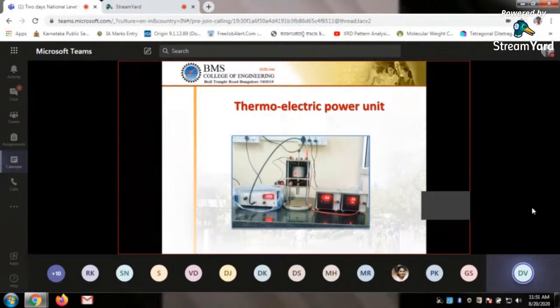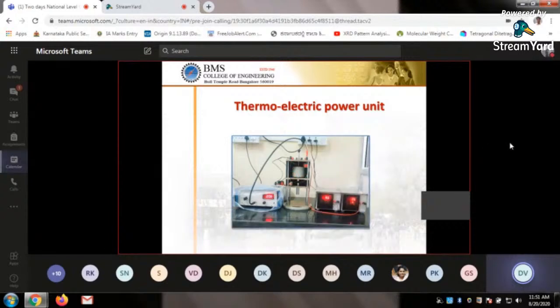This is the higher temperature. We have a furnace here. We can see what the temperature of that furnace is. It is connected to a thermocouple, and we can read the temperature. And the lower one is at room temperature. Usually there is a temperature difference. So this is where we have to keep the sample. The upper surface of the sample is at higher temperature, and the lower surface of the sample is at lower temperature. It means you can keep a water glass here with cold water. It may be 0 temperature, so that the lower surface is at low temperature and the upper surface is at higher temperature. You can see the values also.